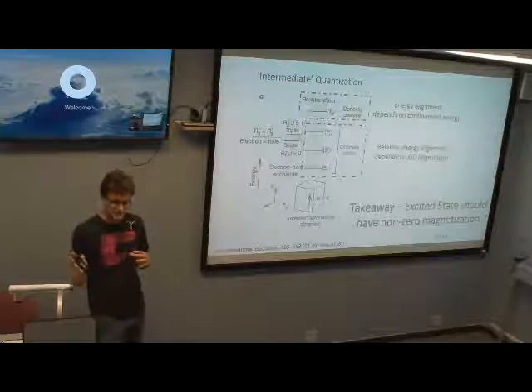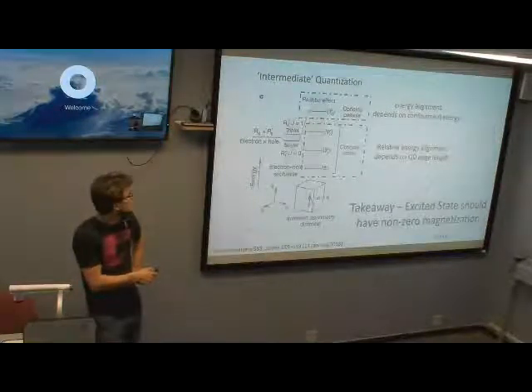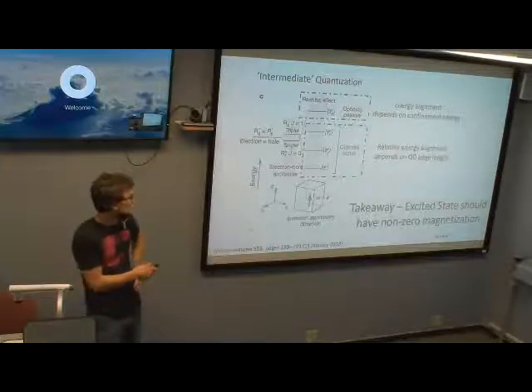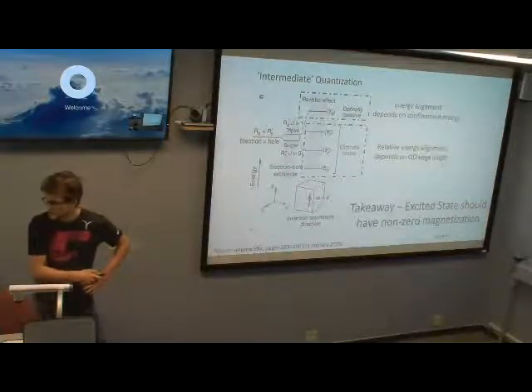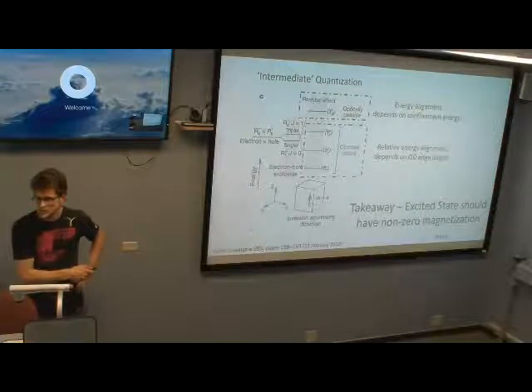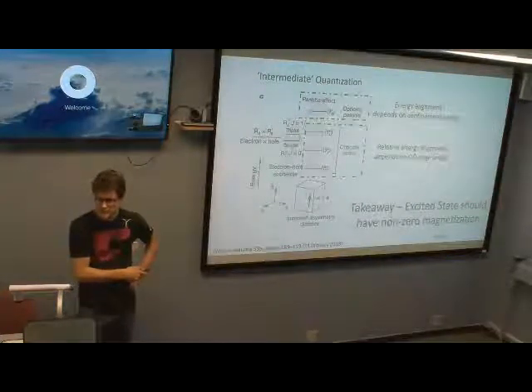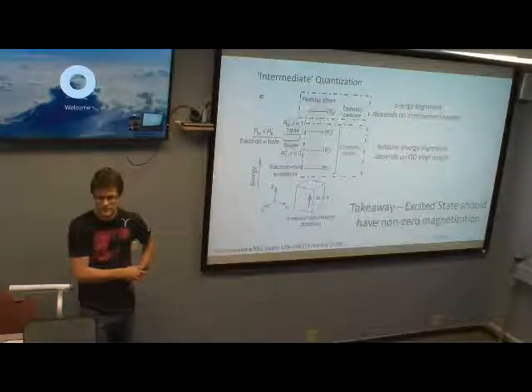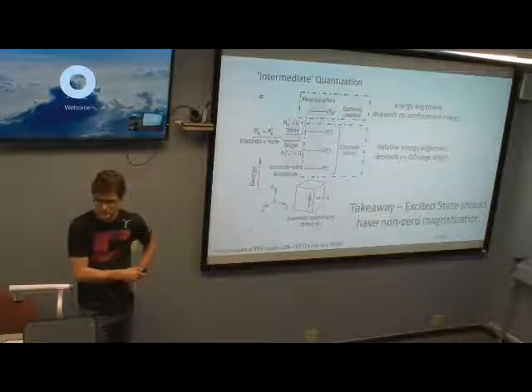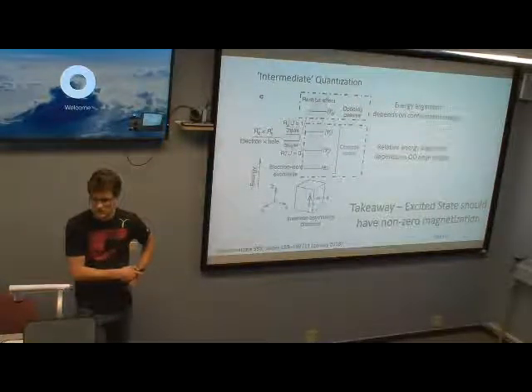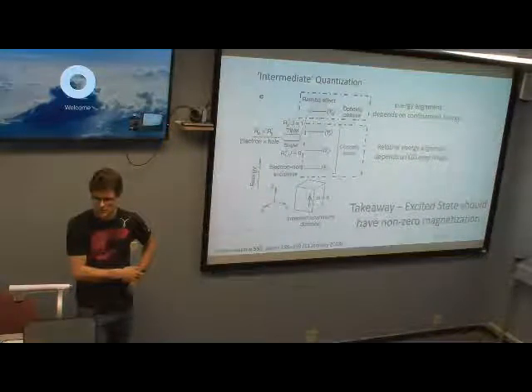Like the dimensions of your bonds relative to each other. And then this energy depends on the confinement energy. So according to Efros, the singlet and triplet excitons flip their order in energy due to the Rashba effect, which is controlled by the size of the quantum dot. But yes, if in your modeling the size is not correct, this flip may not happen, and this could be responsible for lower quantum yield.